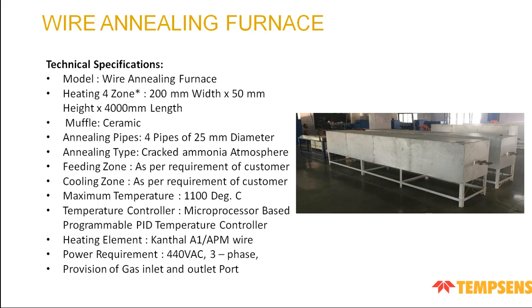Now this is our wire annealing furnace. When we have to anneal copper wires or any wires at a high temperature around 1100 degrees centigrade, this furnace is very useful. It has basically 4 zones of 200 mm width and 50 mm height, and 4000 mm is the total hot zone length of the furnace. The muffle will be used inside this. This will be ceramic, and there will be 4 pipes or 6 pipes as per the customer requirement. We can customize this with 25 mm diameter, and we can also increase or reduce the pipe diameter. The annealing atmosphere is cracked ammonia, and the feeding zone and cooling zone are also as per the customer requirement. The maximum temperature can be 1100 degrees centigrade, and multi-zone controlling can be done, microprocessor based, and we can also provide a programmable controller. The heating element will be Kanthal A1, and there will also be provision of gas inlet and outlet ports.